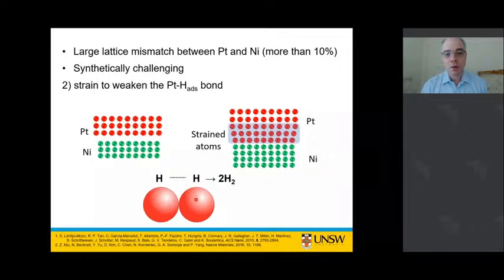And this is important because one of the limits for the hydrogen evolution reaction is actually the hydrogen, when it's adsorbed onto the platinum, tends to adsorb a bit too strongly. It's stuck on too strongly. So if you can introduce this strain, it means that these can come off a lot more easily, and then you can form your hydrogen gas a lot more easily. So we want some strain in there to weaken this platinum hydrogen bond to increase the catalytic properties.